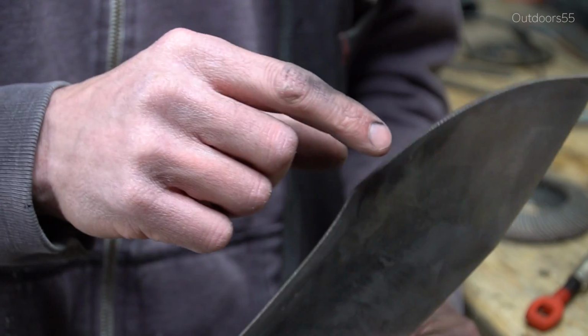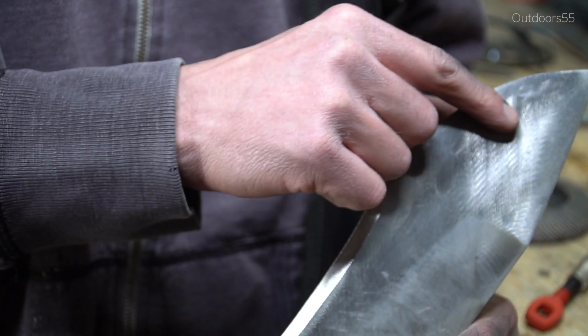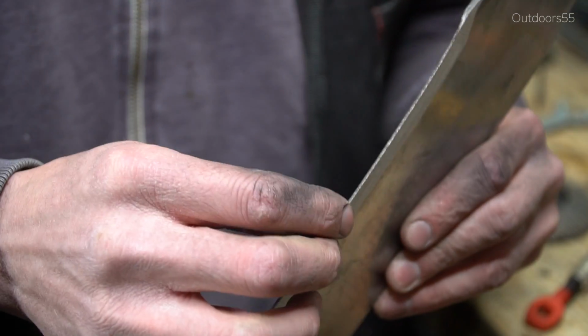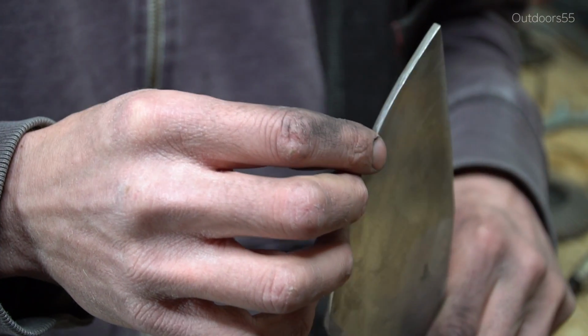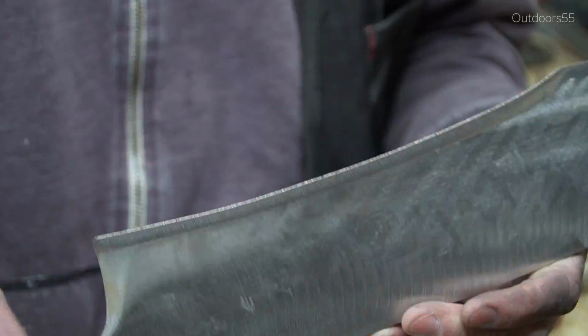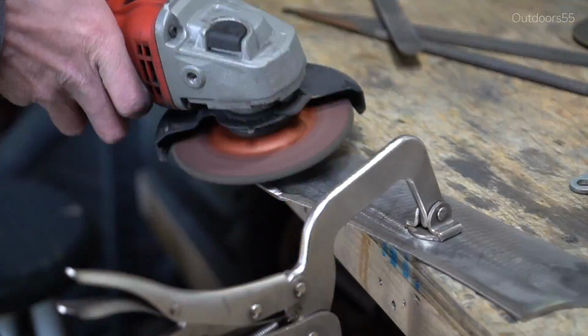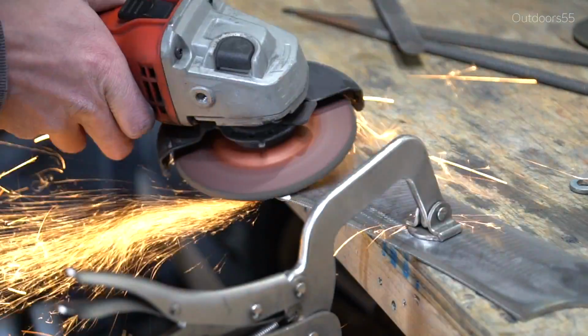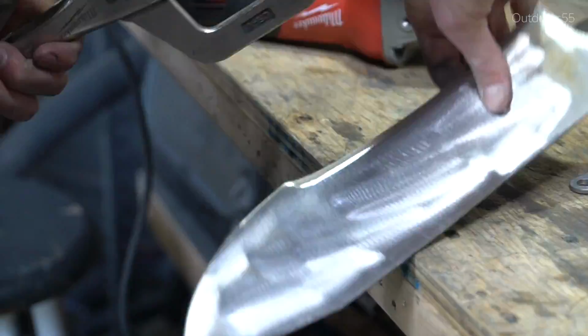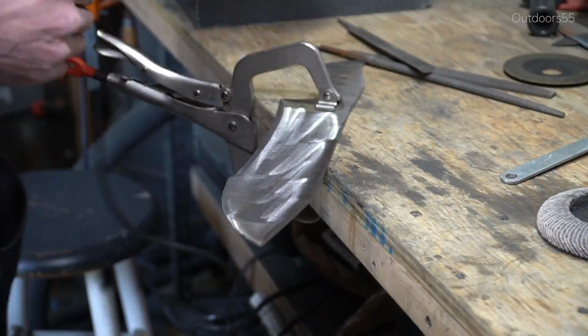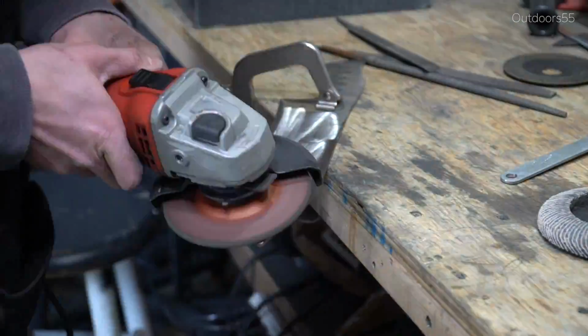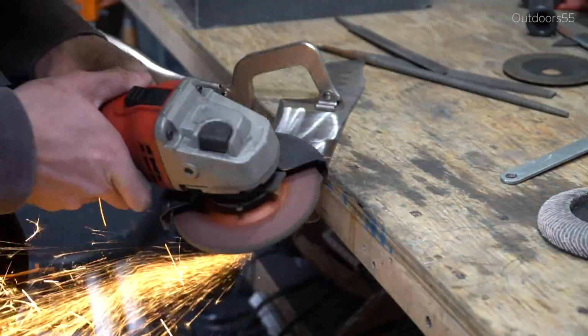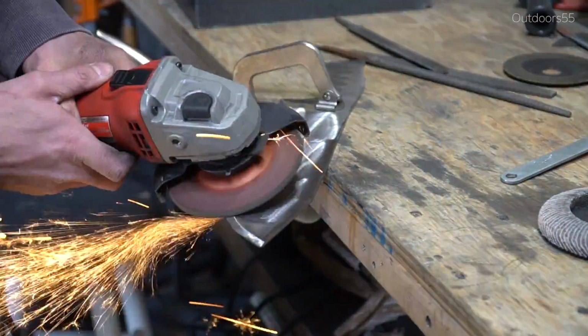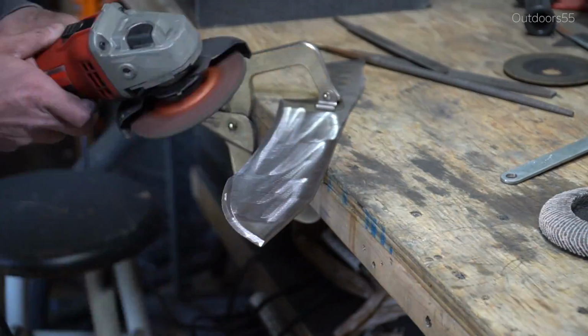So what I'm going to do now is go back and do the same thing to this portion of the blade, and then our bevels will be centered all the way down the entire length of the knife. It's important to note here that you do not want to grind too thin before heat treatment. If you grind your edge too thin, you'll greatly increase your chance of cracking during heat treatment. You want to leave about a dime's thickness there on the edge of the bevel.